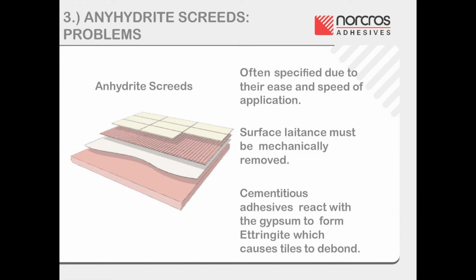The major problem associated with anhydrite screeds is the increased drying times compared to sand cement screeds, as discussed in an earlier slide. Another disadvantage of anhydrite screeds is the weak layer of laitance which is formed on the surface. This needs to be removed by sanding or grinding before tiling can commence. The removal of the laitance will also aid the drying process.